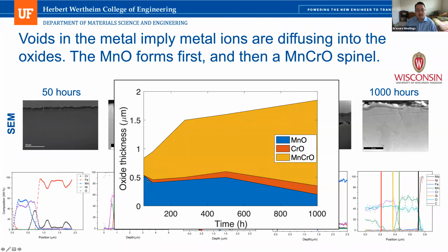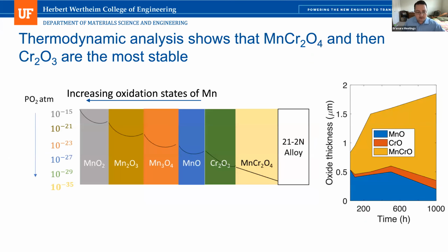Now, at the same time, we have a chrome oxide layer that forms and starts to grow, though it's never very large. But what really is dominating the oxide growth is the growth of this spinel. Now, if we look at this in more detail with thermodynamics, we can start to understand what's going on here.